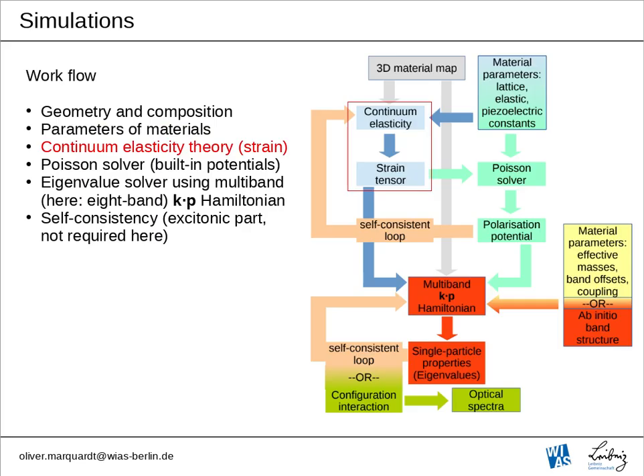In the next step, we run a continuum elasticity module, which gives us the strain distribution in the system. And for the sake of completeness, let me mention that there's also a Poisson solver which computes from strain and piezoelectric constants the built-in electrostatic potentials. Here in this particular case, these are very, very small. So yes, we have them in the simulation, but they contribute only about single meV energy difference to the bands, and they have their extrema at the outer corners of our system, so they really don't play a role here.